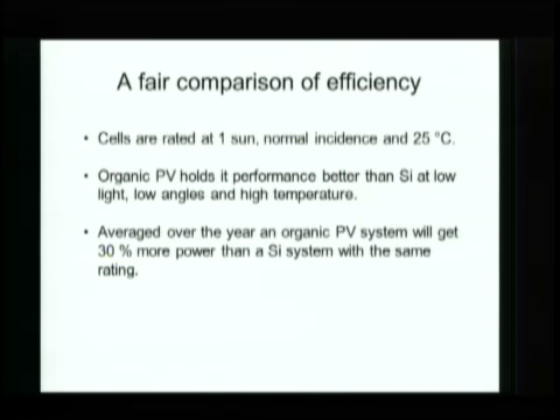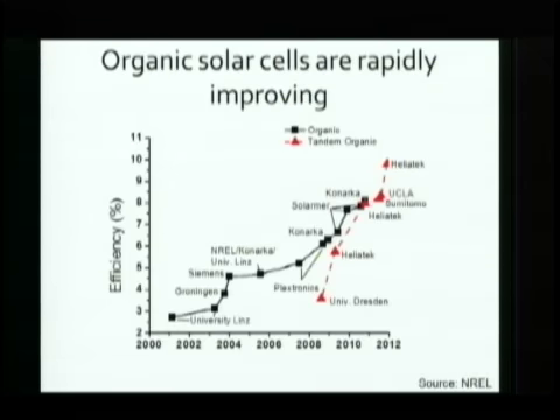And so if you had an organic system and a silicon system both rated at the same power, you'd get 30% more over the year from organic. And so really, to be fair, you need to multiply by 1.3, and this is equivalent to being at 13%. So the gap is not as large as it appears to be. The record for silicon is 25%, and the modules you typically get are around 18%.